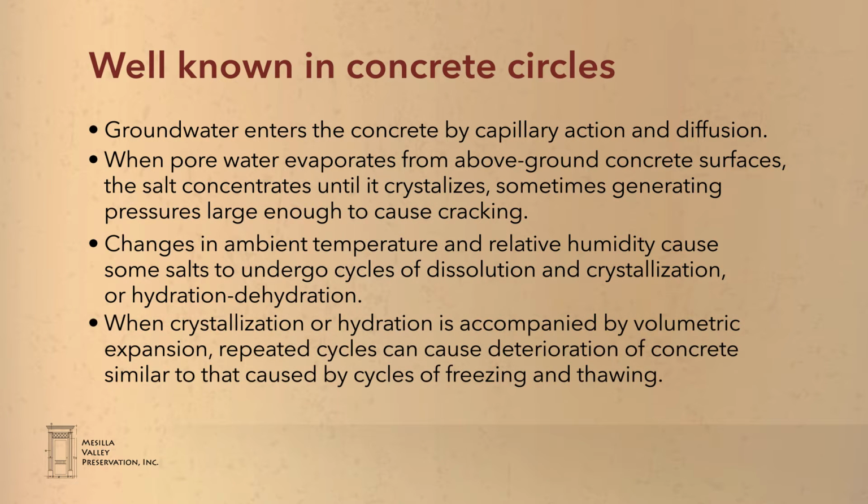I want to emphasize that salt attack is actually a very well-known problem, especially in concrete circles. The concrete industry has understood this process for a while. Here is a description quoted from an American Concrete Institute presentation that describes, in lots of words, the process that we just looked at graphically. Note that in this case they are talking about the destruction of concrete. The last point here is very important. Once the salts are present, they literally are capable of driving this process on their own, creating a microscopic freeze-thaw cycle that can literally take place multiple times per day. We'll talk more about that later.